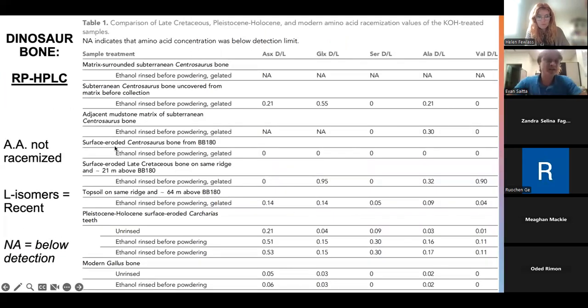Now we can look at the racemization of these amino acids, and we see that in the dinosaur bones, they are not racemized, and they are heavily biased towards L isomers, suggesting that they are recent amino acids. Now, this is, of course, only in cases where the amino acids are in high enough concentration to even be detected. Some of these results are actually below the detection limit.